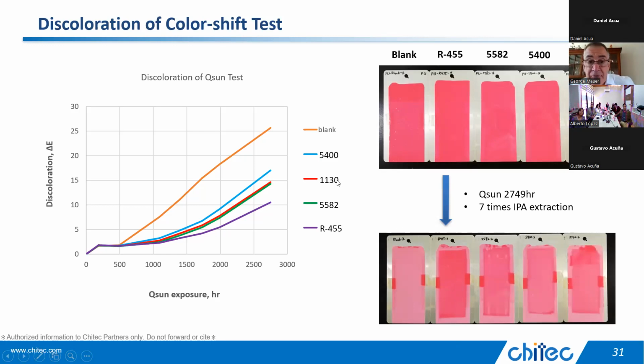And here's the results. We start off with our red, and this red is actually a mixture of the F3RK red pigment with titanium dioxide, which is really just to give it some good hiding and a consistent color to look at. And you can see down below, the R455 is clearly the best for color retention. And you might wonder why the 5400 isn't better. It's kind of middle of the pack. It's marginal. It's clearly better than nothing, which is the blank over here. And the reason for that is it doesn't protect you out at 360, 370 nanometers. So this is a case for this particular pigment where having the benzotriazole is an advantage. It gives you that broader protection.